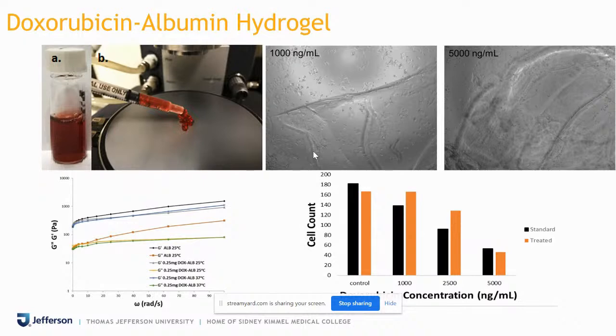We loaded drug into this gel, and we loaded doxorubicin in the albumin. We performed the rheology. We can see the frequency sweep experiment again confirms that the gel is physical in nature compared to the native albumin gel. And then we performed a live dead assay, the cytotoxicity assay, for the drug loaded albumin gel, where there was a substantial reduction in the cell viability of the MCF7 cell line.